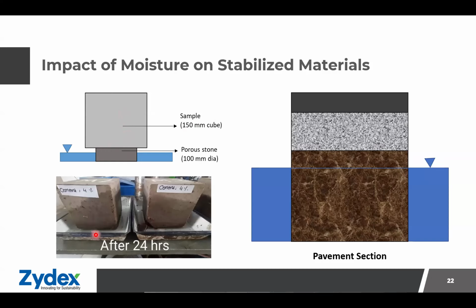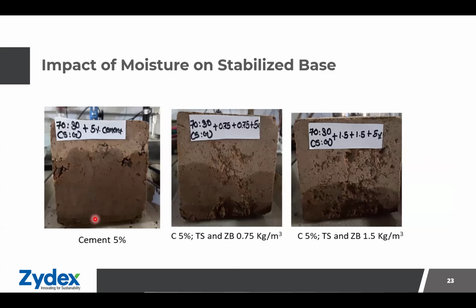The cube is kept on the porous stone, which is under a water bath. And here you can see, due to the capillary action, the water has been taken up by the sample. And depending upon the additive or the cement content, the capillary uptake varies. So this is another slide where I'm showing only cement of 5%. We can see after 24 hours, the capillary uptake is significant, where the water has gone up to almost 75%, three-quarters of its height.